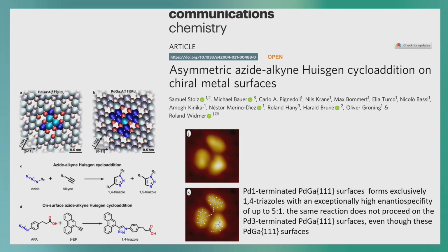But I think this is interesting, and it's really going in the same direction as what another group at EMPA does. They already looked with UHV methods at the asymmetry on the surface of palladium gallium, and they see for this chiral addition also strong enantiomer-specific reaction up to 5:1. So maybe this material is something where we could think about asymmetric heterogeneous catalysis.